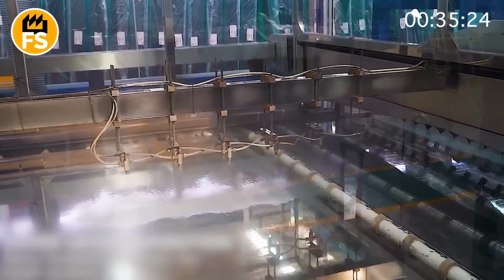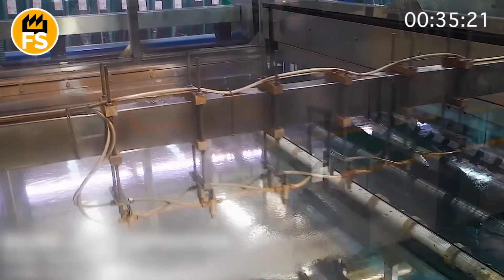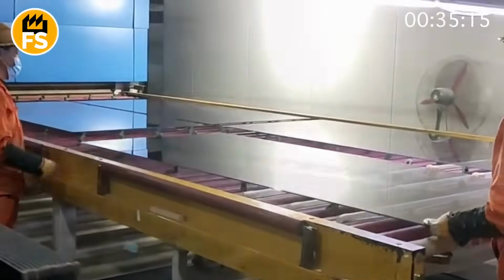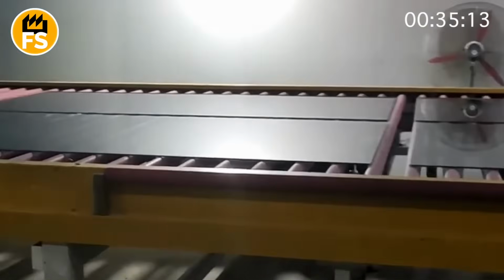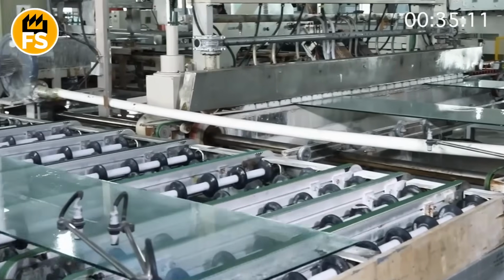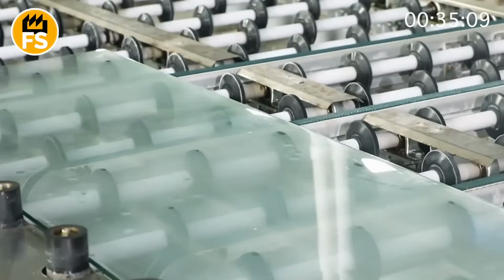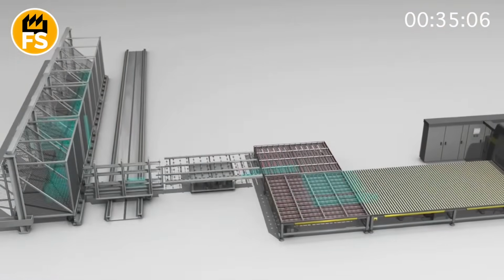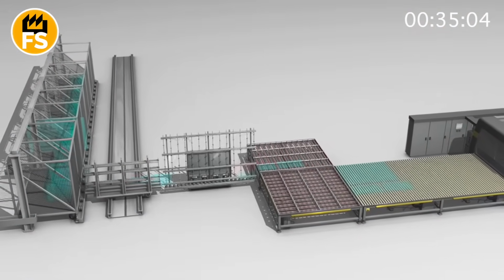The outer surfaces of the glass instantly solidify, harden, and compress, forming a strong, hard outer layer. But inside, the glass still remains hot and plastic. Over the next few moments, the core of the glass also begins to cool, and, like any material, tries to contract. But it cannot do so freely, because it is already held by the cold, hard outer layers.